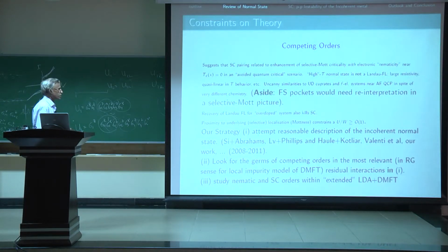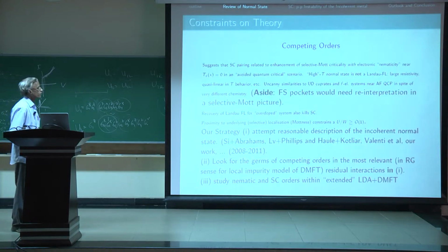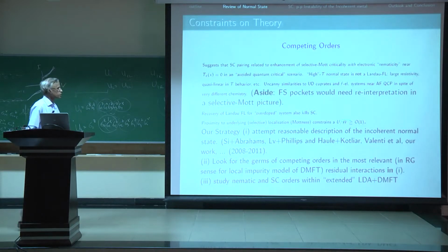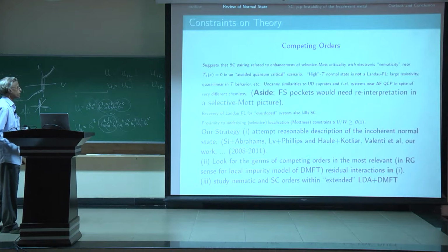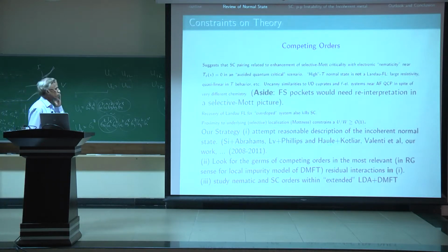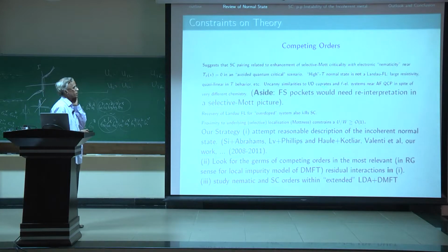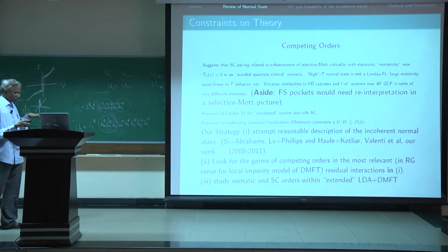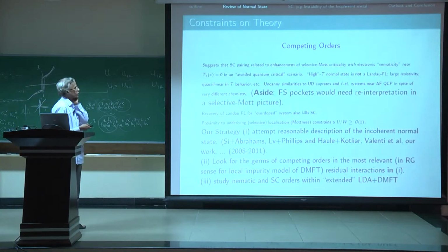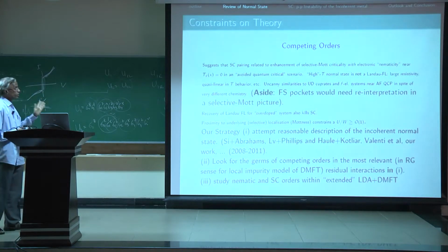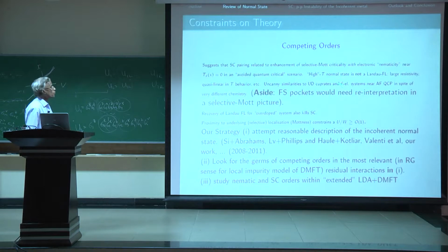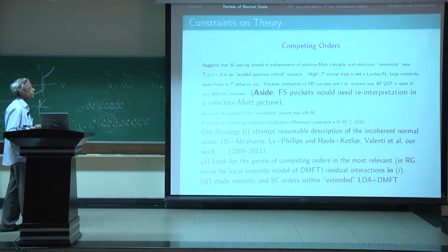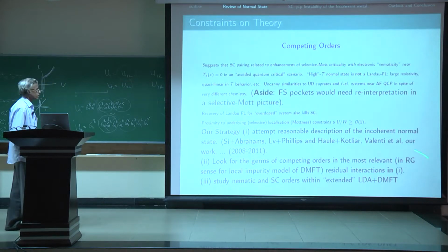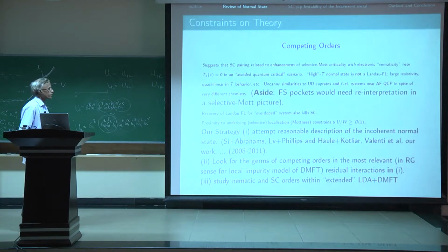Okay, so the first step was to basically ask this and see whether a reasonable description could be achieved. But then if so, the idea was to basically look for the germs of competing orders in the most relevant channels in the residual interaction, which basically should arise in such an incoherent metal, because it cannot continue down to 0 temperature. You would need to quench the large entropy of this strongly fluctuating state before you went to the T equal to 0 limit. And so relevant residual interactions must destabilize this incoherent metal. And so whether that could be achieved within a starting point which would be capable of describing normal state incoherence was the issue.